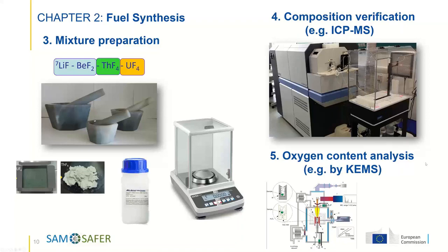And the fifth one, a technique that also requires quality check of the salt: very often we are asked what is the oxygen content or residual oxygen content of the salts. Oxygen is a very light element, and it's very difficult to identify with techniques like SEM or EDX, which we would use for higher cations. So it's not straightforward, but very recently we have found maybe a very good way for the future, which is to look for residual oxygen or oxides by evaporating the sample completely using our Knudsen cell facility. I will show this when I describe how we measure vapor pressure, so I don't have to spend that much time on that technique now.